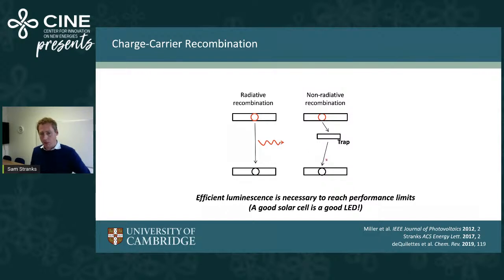So this is non-radiative recombination. This is problematic in a solar cell. It means it's a power loss in the solar cell. So what that means is, using light, we can actually tell how many traps are there, because the absence, when we don't have light coming out, it means there's many of these traps or many of these defects. And what that actually means is that efficient luminescence is very important for a solar cell, and a good solar cell should actually be a good LED. It should also emit light really well. And that's a really important concept that will come up a bit in this talk.